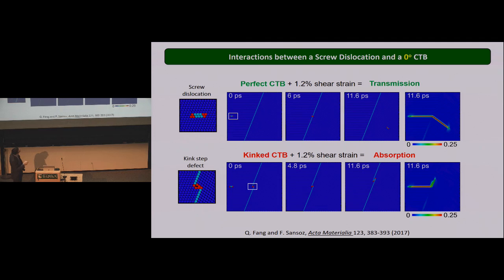And by cross-slip, we'll go to the next grain here. So this is the path or the trajectory of the dislocation going through the twin boundary. And now we repeat the same thing, but we introduce our kink step defect. This one is actually even smaller than the one I presented before. But it happens that the dislocation hits the defect directly.